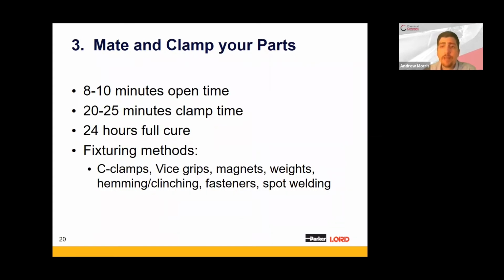So the final step is to actually mate your parts and fixture them somehow so that they don't move until the handling time is reached. As Angela mentioned earlier, the 810/20 has 8 to 10 minutes of open time and requires 20 to 25 minutes of clamping time until that handling strength is achieved. Once that handling strength is achieved, it's ready to move on to the next operation. But do keep in mind that the adhesive will still take a full 24 hours to reach full cure.